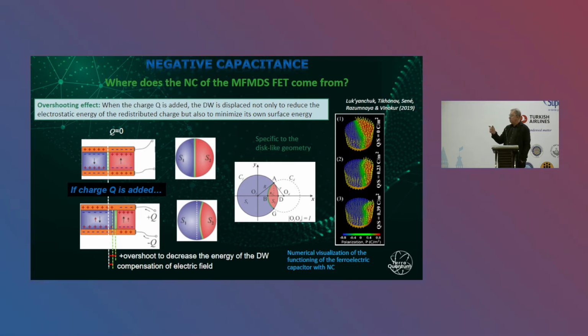If we make this nanoparticle in a disk shape, then if we apply a charge to the plate, in order to compensate this charge, this domain wall should move. And since it moves, its length becomes smaller, and the area. It means that it decreases the surface energy. Then it actually overshoots, because it would love to move a little bit more than it's obliged to due to electrostatic effects. And if it moves a little bit more, then the electric field which appears there overcompensates the electric field due to the applied charges, and it means that we have negative capacitance in our nanoparticle.